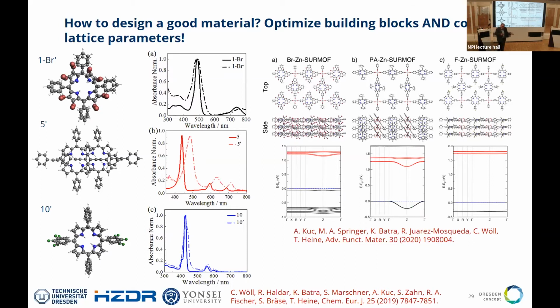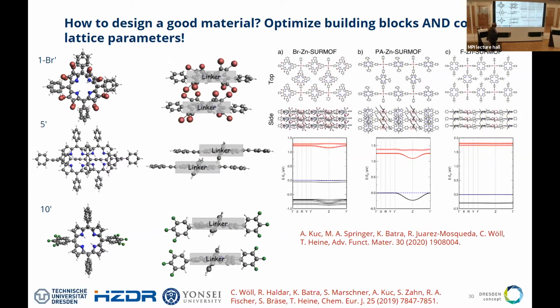And if you look along the stacking and you zoom in, you can see here that these porphyrins, which are our linkers, stack the same way as you would have the carbon units in graphite. Okay, so you have the same kind of stacking like graphite that gives you that dispersion. The dispersion gives you indirect bandgap. It also gives you redshift. It's exactly what you would like to have. That's the way you can actually tailor such a material.